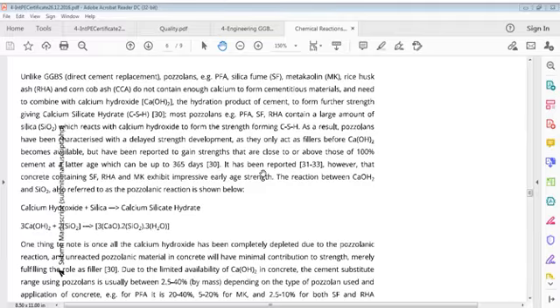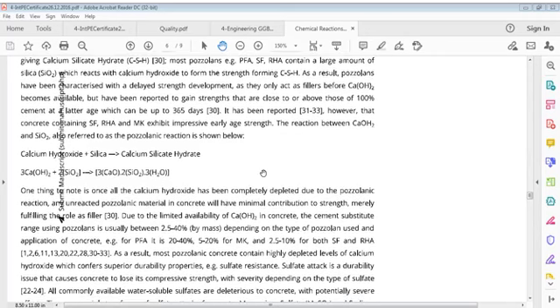Most pozzolanas, PFA, SF, RHA, contain a large amount of silica, SiO2, which reacts with calcium hydroxide to form strength-giving CSH, calcium silicate hydrates. As a result, pozzolanas have been characterized with a delayed strength development, as they only act as fillers before Ca(OH)2 becomes available, but have been reported to gain strengths that are close to or above those of 100% cement at a later age, which can be up to 365 days.